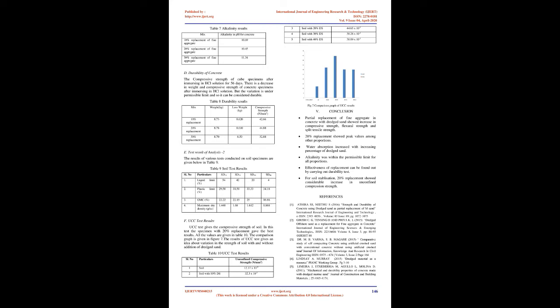The cube specimens of normal concrete and cubes with 10%, 20%, 30% replacement of fine aggregate were cast. The specimens were made using 53 grade OPC cement, M sand, dredged sand, 20 mm coarse aggregate. From the results obtained, it was observed that the compressive strength of concrete using DSS as partial replacement is satisfactory up to 30% replacement. In case of split tensile strength and flexural strength, the results were satisfactory in all proportions. The results of various tests are shown in Table 5 and graphical representation of compressive strength is shown in Figure 6. B. Water absorption test on cubes.